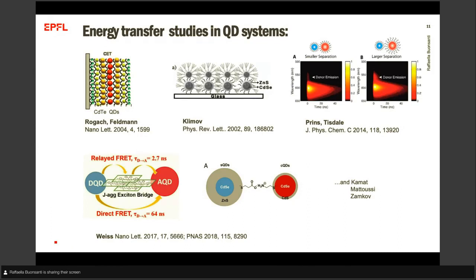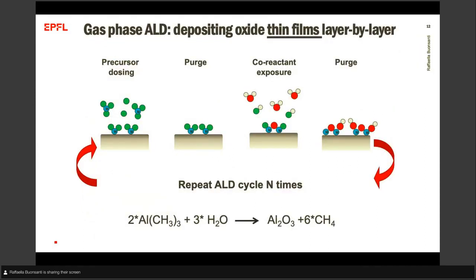So we decided that our spacers were going to be metal oxides, and the best way to deposit thin films of metal oxide and to control the thickness, so that we could control the spacing between the quantum dots, is atomic layer deposition. So traditionally, atomic layer deposition is conducted in gas phase. And the first material we wanted to deposit is alumina. And what you do to deposit alumina in an ALD chamber is you pulse the trimethyl aluminum. Then the trimethyl aluminum reacts with the surface of your material. Then you purge, so you eliminate the excess reagent. Then you expose to water, and then you purge. And water starts to react with the trimethyl aluminum on the surface.